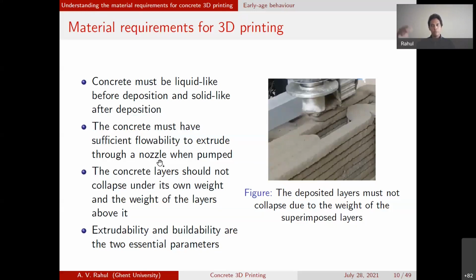The ability of the concrete to be pumped up to the print head, we call that extrudability, or the ability for the printable concrete to be pumped until the nozzle. And then once it's extruded from the nozzle, the ability for it to retain its shape, the fact that you can build one layer above the other, is what we call buildability. So these two are critical parameters that we need to assess for developing 3D printable mixes.